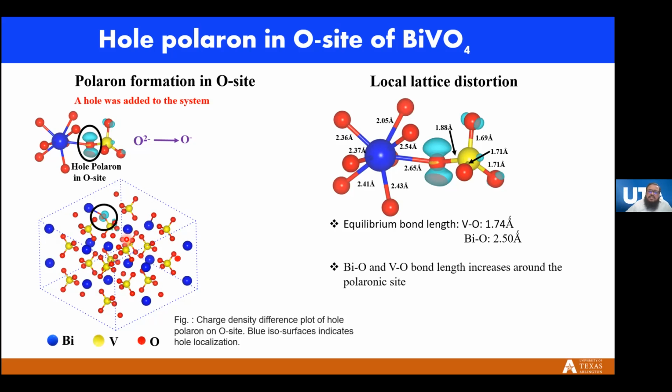Hence, if I want to stabilize a polaron in a crystal with GW, we have to first get the polaron-containing structure, and then I can apply GW. GW is basically pseudo-particle, many-body corrections, but it is not a total self-consistent energy calculation.